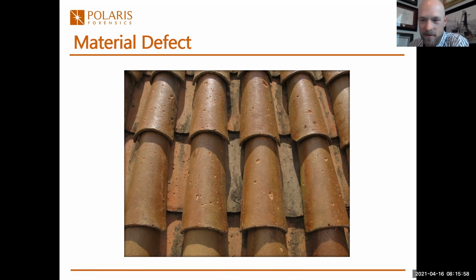And I was finding these same spall marks, which was basically the smoking gun that told me that this wasn't related to hail impact. I'm not sure if you can see it in this image or not, but at each of these little spall marks, there's like a little white dot or speck. It turns out that when they were manufacturing this clay tile material, it was manufactured inadvertently with limestone inclusions. That limestone material over time absorbed water, it expanded, and it created these surface spall marks. This is a good example of what a material defect might look like.